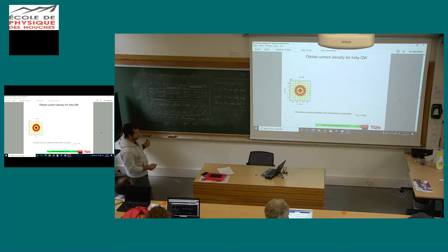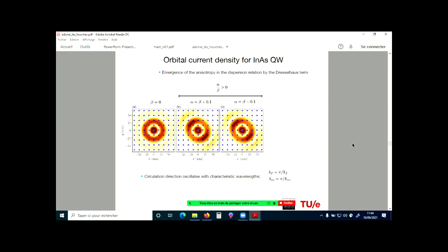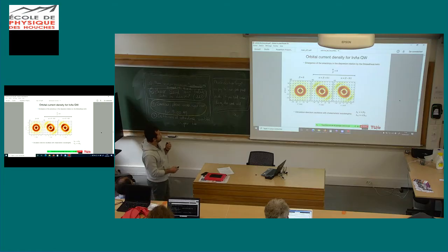And for the case of just Rashba, it resembles very much, the characteristic wavelength is very similar to the Friedel oscillations in charge. And it has a structure that oscillates in different directions. A nice thing that also happens, of course, is when we include both terms, so Rashba and Dresselhaus together, and you see that it's stretching along the symmetry axis, that's 3 pi over 4.